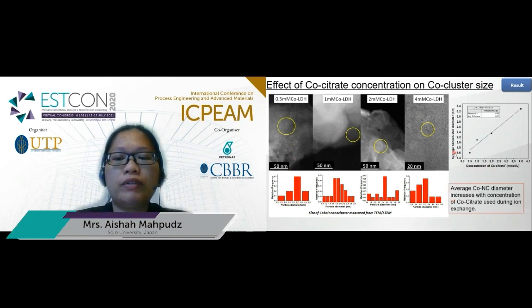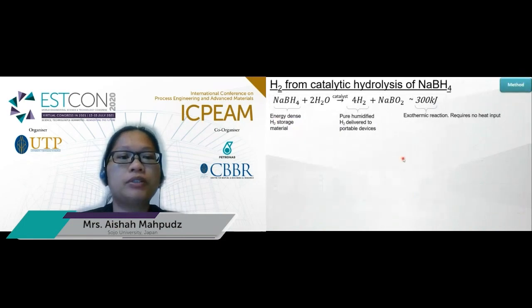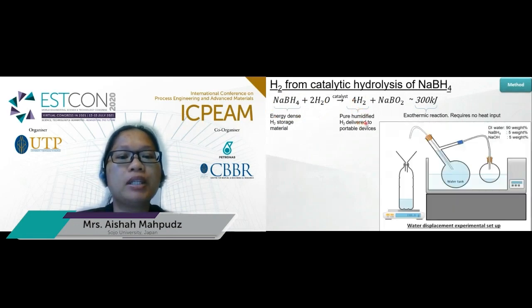And based on the average cobalt nanocluster diameter versus the concentration of cobalt citrate, the plot of the graph indicates that the average cobalt nanocluster diameter increases with the concentration of cobalt citrate. So the catalytic activity is evaluated from sodium borohydride hydrolysis. Sodium borohydride is basically an energy-dense hydrogen storage material, and it reacts with 2 moles of water, producing pure humidified hydrogen that can be delivered to portable devices for energy.